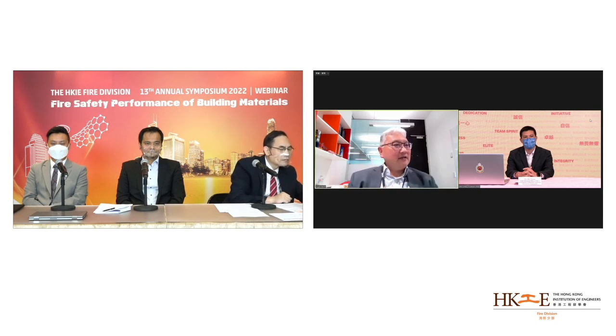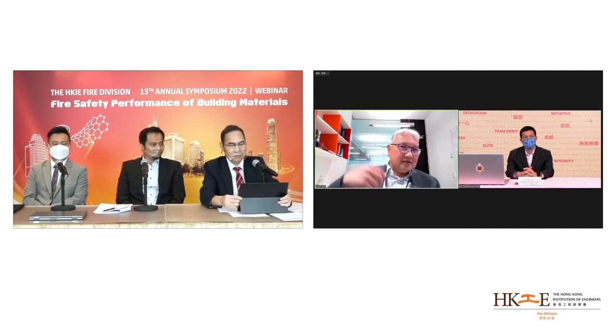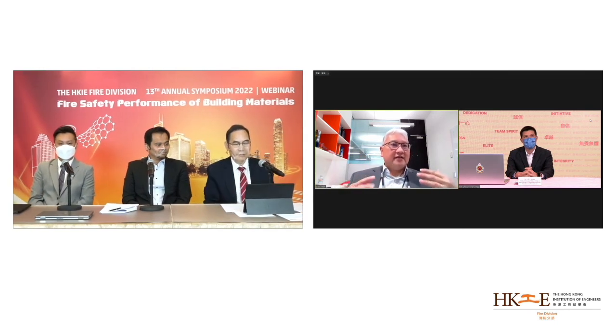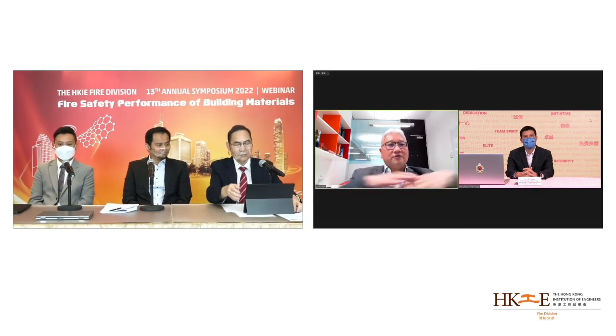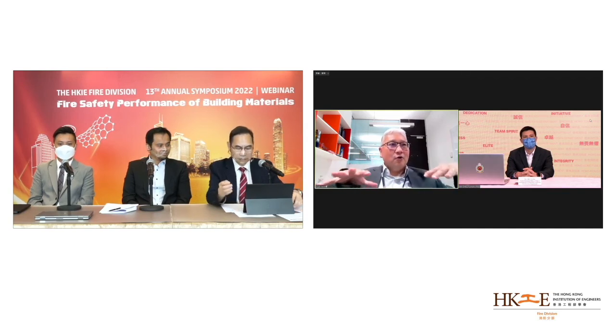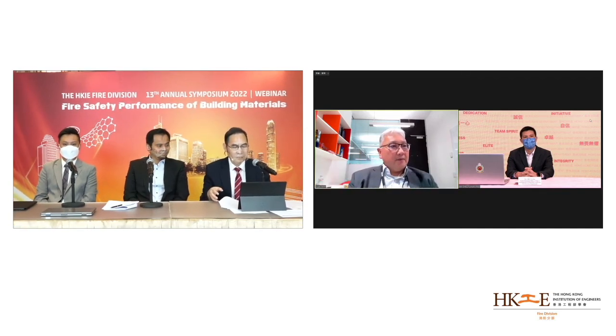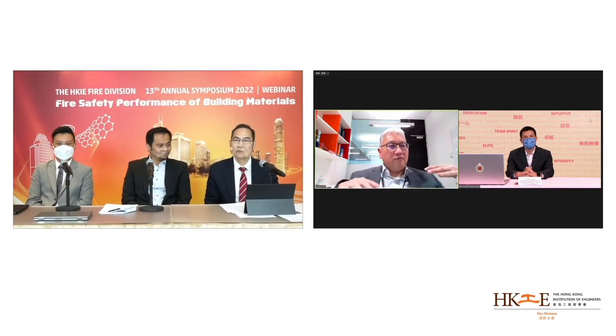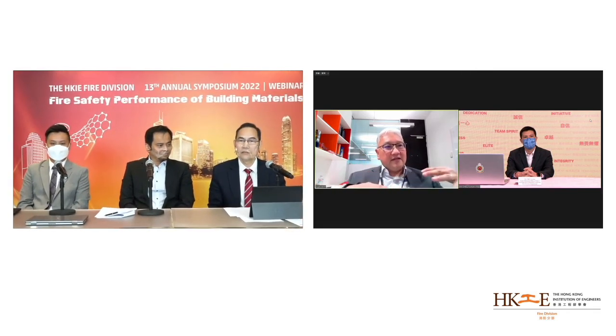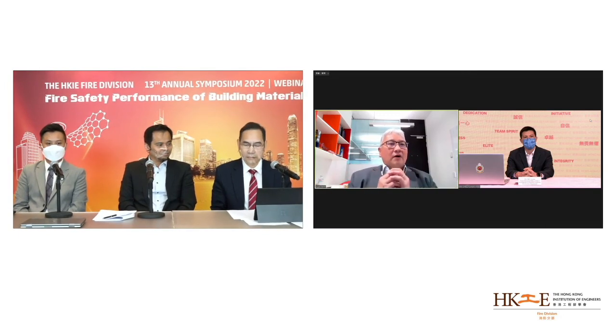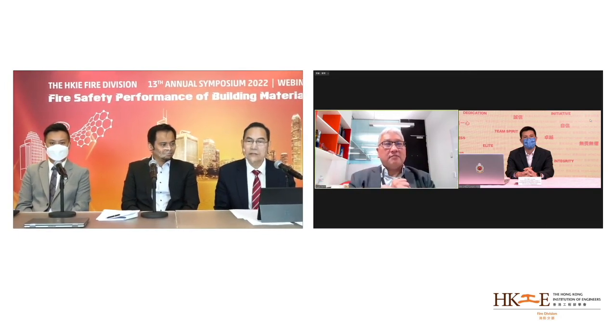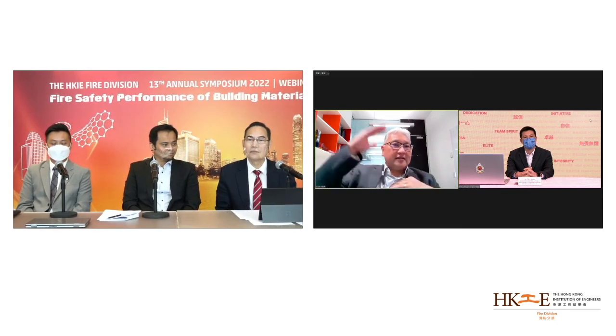The chitosan itself is an extract from prawn shell. So you just mix the solution with the MXene, and the MXene will interlock with each other to form a coating. And that coating is so effective, where the MXene itself helps to disperse the heat, while the chitosan holds the materials together to shield it from the external heat as well. That's how both of these materials work.